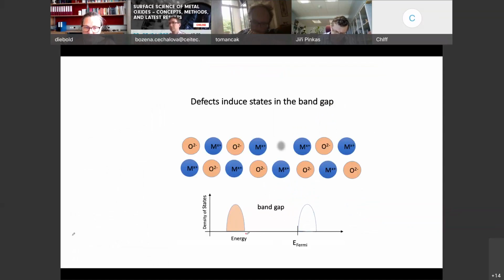So for TiO2, I told you we have a 3 eV band gap. The Fermi level, that's the reference level, is here. We look at these states when we have a negative bias voltage of 1.2 volts. So we shouldn't really see anything. The reason why is because there are no states in the band gap. There's no way to tunnel.